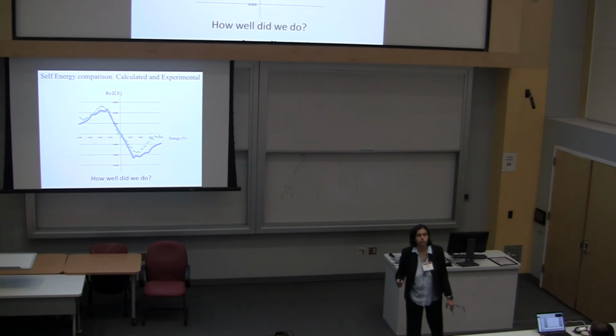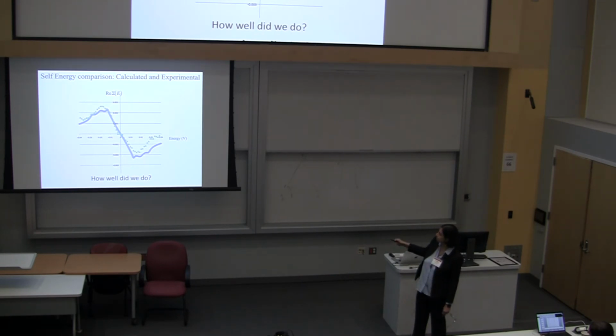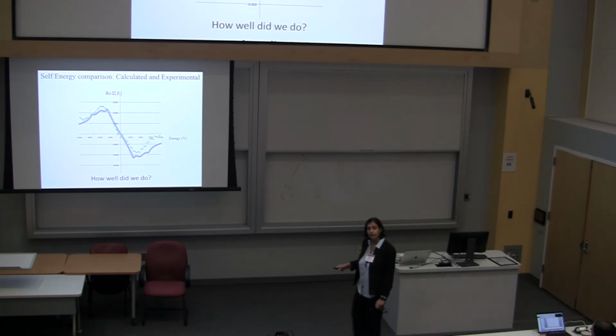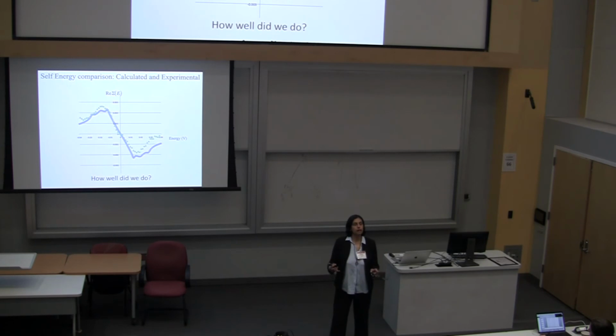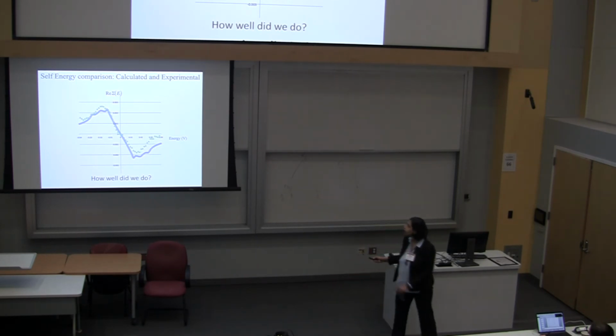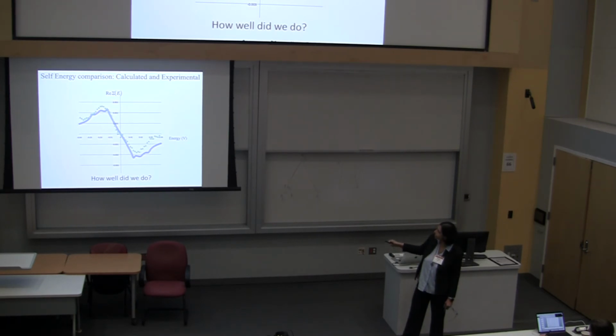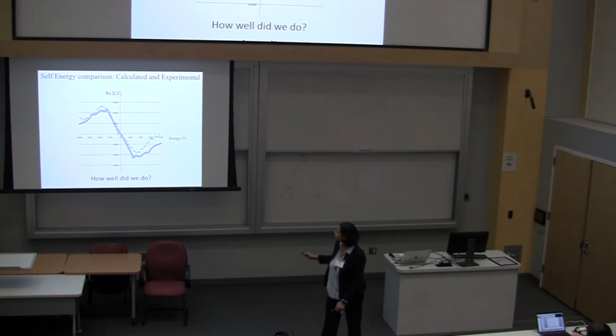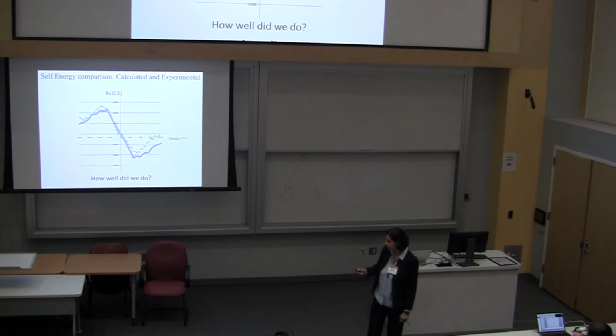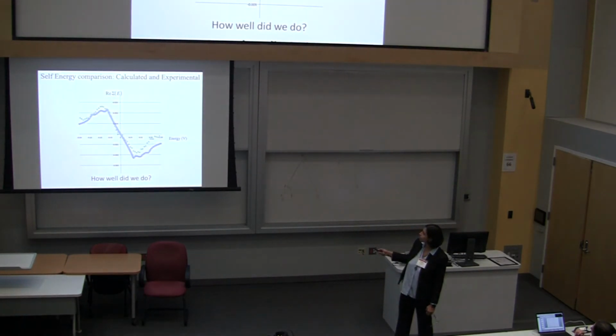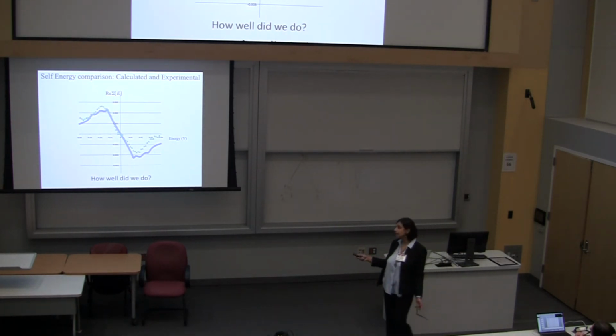And you can ask the question, how well did we do? Let me try to answer it in a few different ways. The first thing, the magnitude of the change. This is 2 meV, by the way. That is very, very close. So this tells you that at least we got the approximate strength of the coupling between the electrons and the phonons right. However, look, the calculated self energy has all of these little wiggles, and our experimental self energy is missing all these little wiggles. As it turns out, if we had actually wanted to use our experimental data and invert it to get alpha squared F, without the little wiggles, you will not get an actual alpha squared F. So the answer is we did pretty well on some scale.